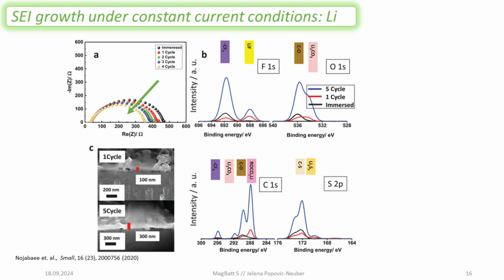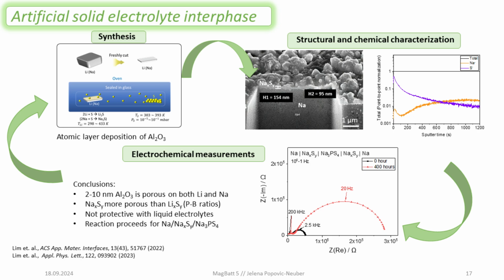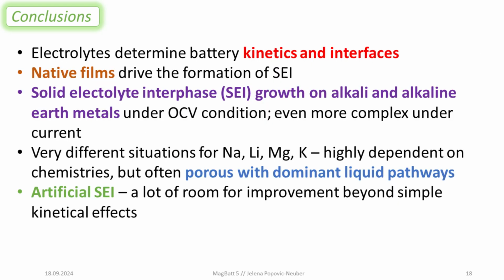So this was the beginning, and I talked about SEI growth under open circuit voltage conditions, but the next step is actually to understand what happens under cycling, because this is the real situation. We can, of course, build artificial SEIs, but we have shown that in the case of sodium, we can never really make a fully dense SEI, even though they appear so. So I see already Max standing up, so I'm going to fast forward to my conclusions.